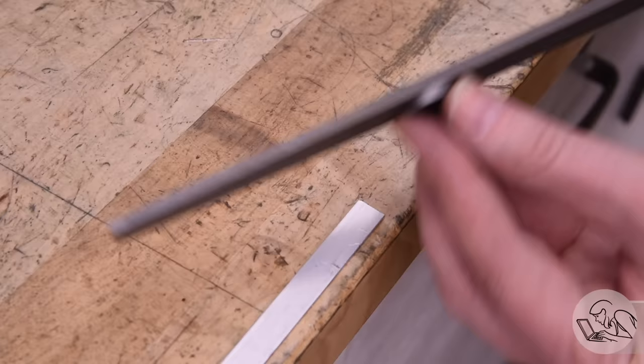With a long skinny tool like this, it's helpful to know another technique for tempering, which is how tools like this are typically tempered, and that is you apply the heat at one end only. And you can see I'm, again, just kissing the far end of it with the torch and watching that color develop. You can actually see the colors moving down the part as the heat travels down the part. So you can watch for that light yellow color to reach the business end of your tool and then stop and dunk it in the water at that point.